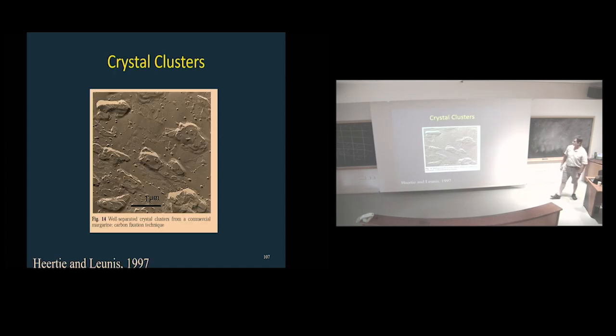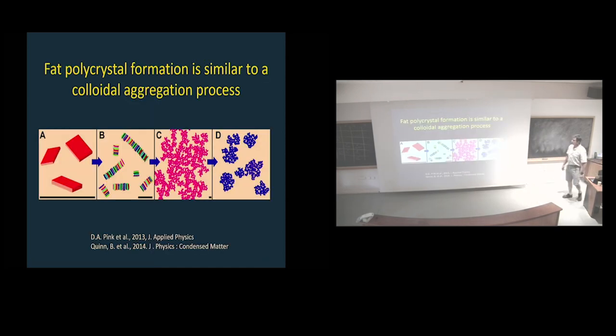And so we went into the literature, and of course, it had to be Heertie again. He had these pictures of these things, and he calls them crystal clusters. And we're like, damn, there must be crystal clusters. So why don't we make color pictures out of it and do Monte Carlo simulations with David Pink out of St. Francis Xavier. So in the end, we managed to create a nanoplatelet, and I'll show you how. Maybe these things aggregate via the 001 planes and form these linear structures, which then can aggregate and form mass fractal things, and then the whole thing keeps on aggregating until who knows what.